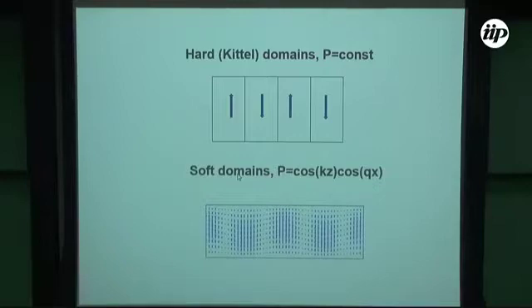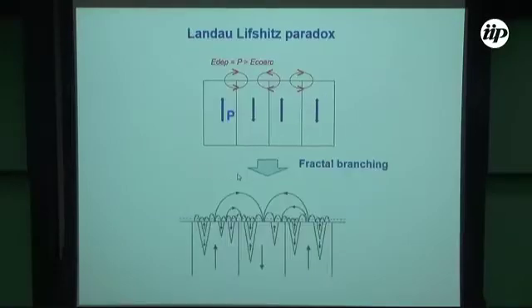And also the polarization goes to zero at the film surface, which is not a boundary condition. This is just a question of minimization of the function. So the system would not like to have the depolarization charge at the surface. Actually, it's very interesting because this is another story of the so-called Landau-Lifshitz paradox and Landau-Lifshitz fractal branching. When Landau and Lifshitz discovered that the magnetic system should split into domains because of the depolarization field effect, they considered what happens near the surface.